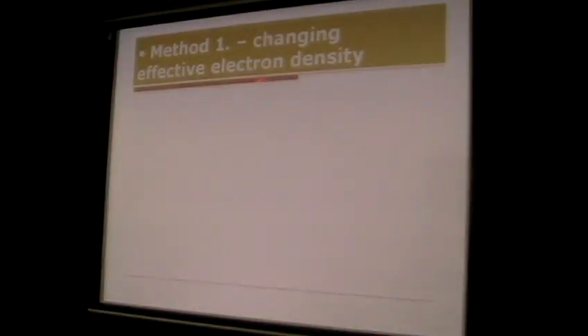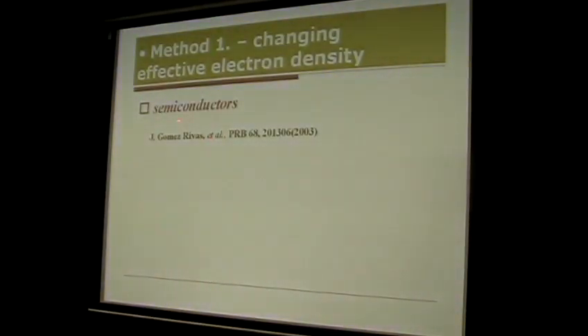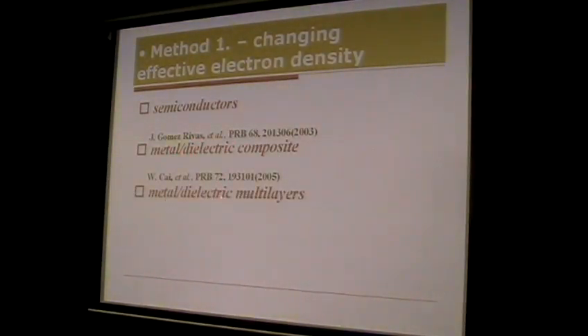There are quite some methods. The first method is to change the effective electron density so that you can change the plasmon frequency. You can use the idea of semiconductors. You can use the metal dielectric composite and also metal dielectric multilayers. By adding some dielectric layer inside the metals, you can decrease the electron density so that the plasmon frequency can be lowered.